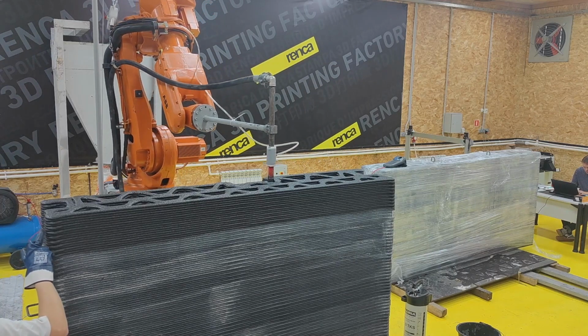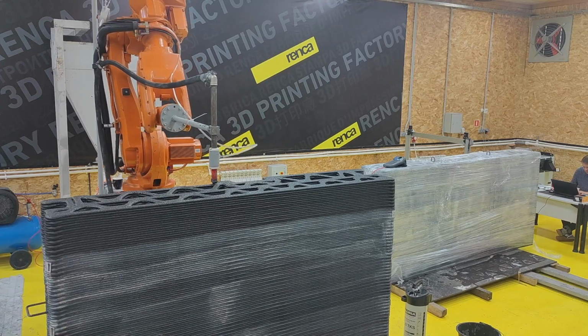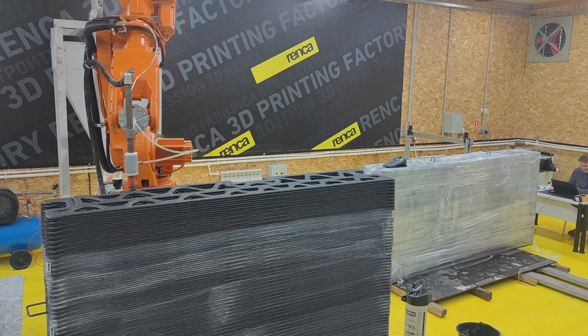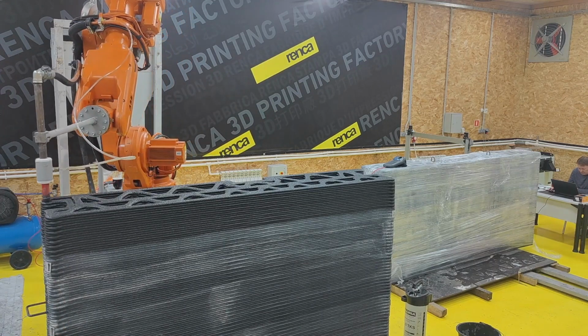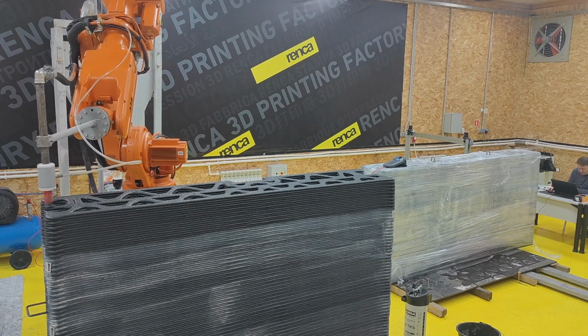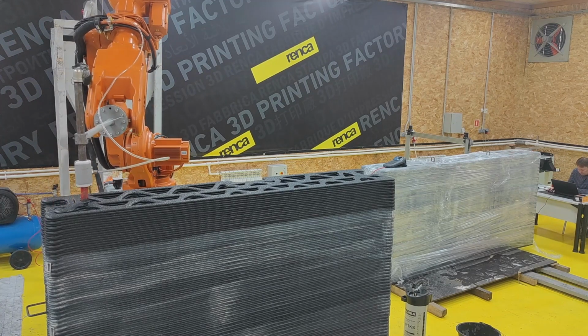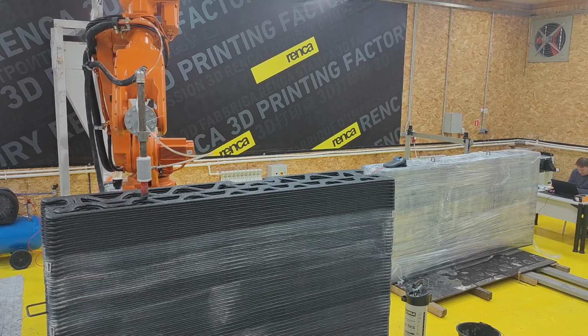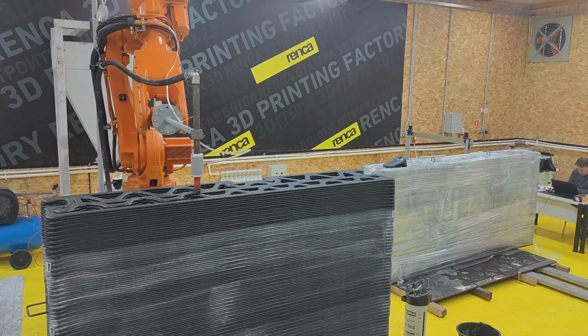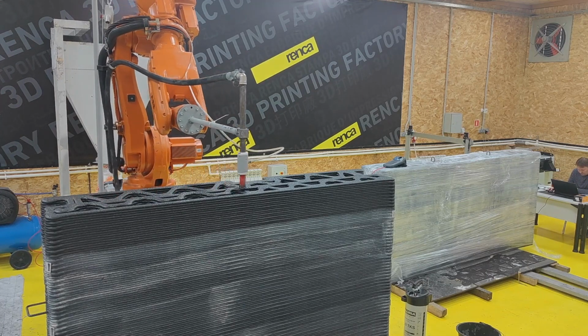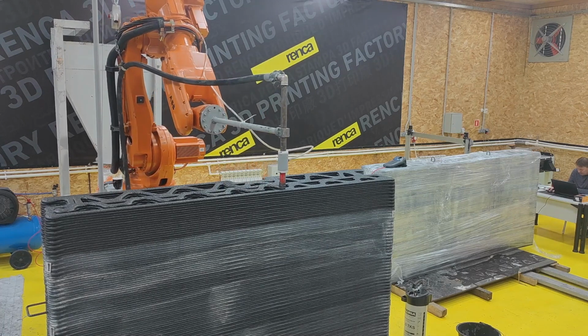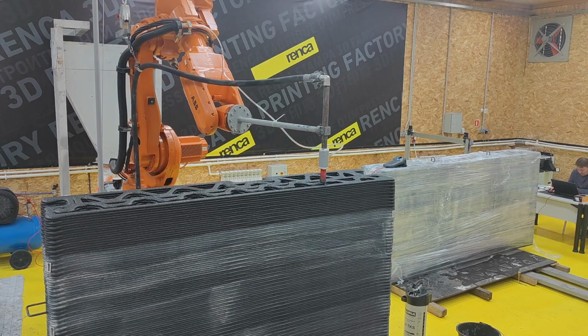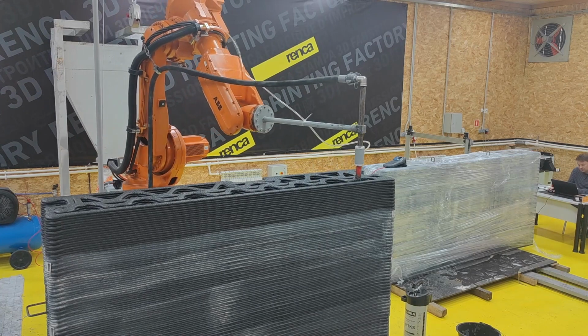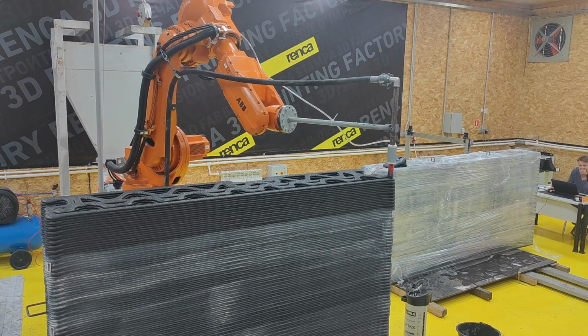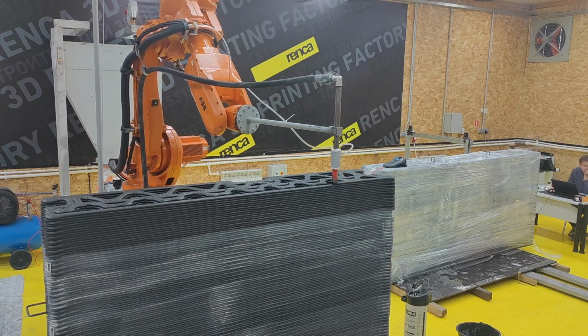You can move the object and start using it in about a week, because this is a fast setting geopolymer, but it will still continue gaining strength after 20 days. It will gain even more strength in 50 days and then in 90 days. So it's a continuous process which will continue up to 180 days and even maybe more, but more research is needed on the long term.